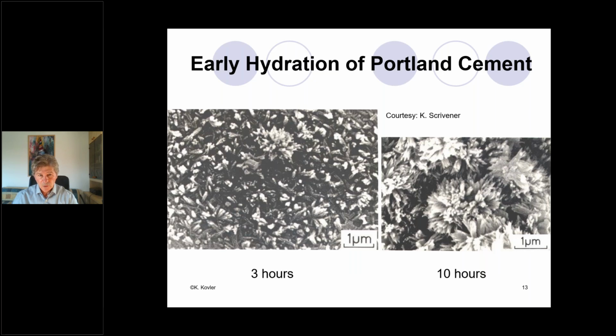From a very early age, we know very well how Portland cement is hydrating. We have 3-hour and 10-hour microphotographs. We can see the hydration products growing outwards from the cement grain. The porosity is changing, is reducing. Instead of the pores, which we call capillary pores, we have newly formed hydration products. Very often they are noted as CSH, calcium silicate hydrates.